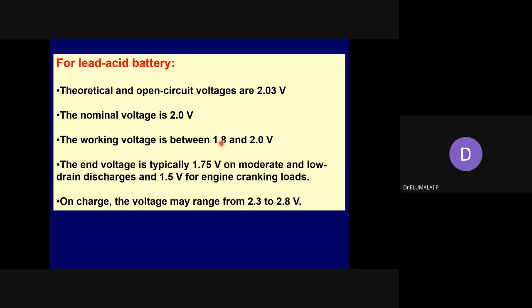In the worst cases, in the case of a traction battery, you can go up to 1.5 volts, not less than that. If you go less than that, it is not possible to recharge the lead acid battery. Electrolyte becomes more watery. You will have only water, not sulfuric acid. If you have only water, how is it possible to pick up the charge? How can the battery pick up the charge? Because there are no moving ions. In sulfuric acid, the moving ions are H plus and sulfate. But in water, only H2O is there. There are no moving ions.